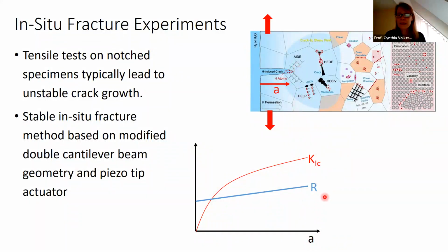Now, there's a resistance of a material to crack propagation that depends upon changes in the defects, many different processes that can occur in the material, and they're summarized together in something that's called the crack resistance, or the R curve. It may go up, it may go down for material, it depends what it is. But the point here is that if this K1C gets larger than the resistance of the material to propagation of the crack, then the crack becomes unstable. And so if I have a geometry where I'm loading the specimen, as I show here, where I have a crack and I'm pulling on it in tension, it's almost certain that it's going to become unstable.